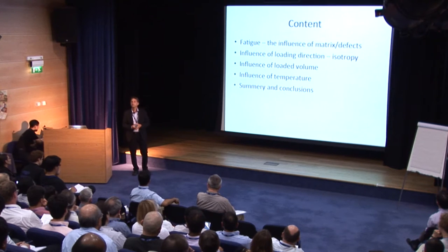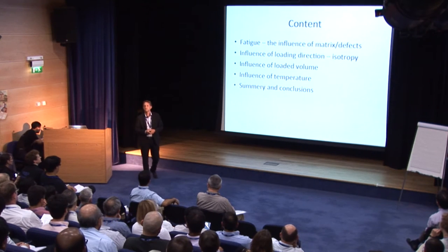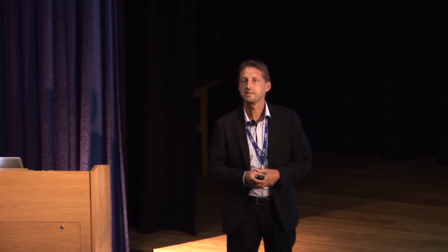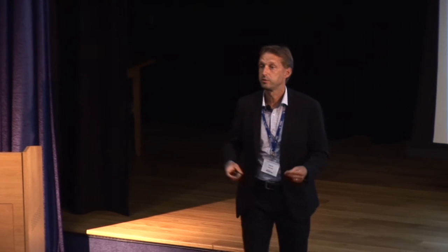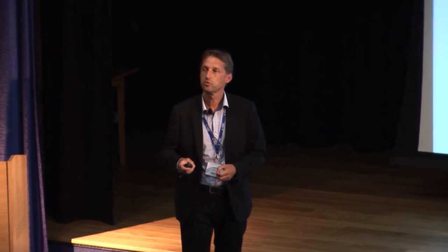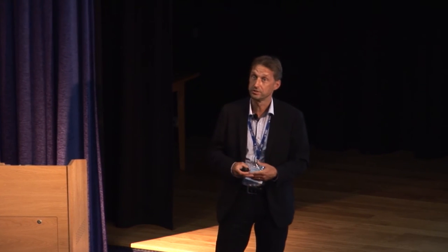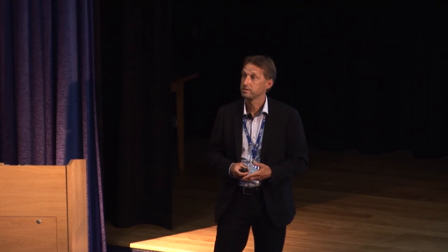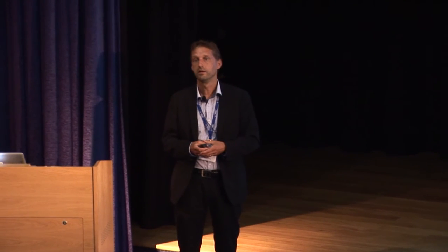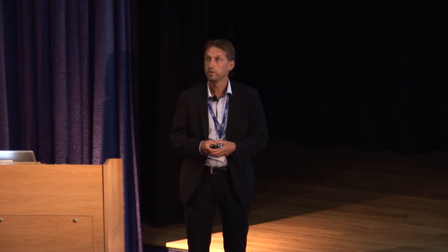We have been working quite a lot with very complex loaded components, and we realized that a lot of the fatigue data for high-strength steel that you find in the literature is normally obtained from the most beneficial direction from a steel producer's point of view, while a lot of components today are loaded in much more complex directions. This means that thinking about isotropic properties becomes more and more important.